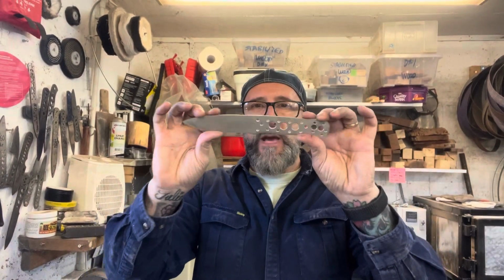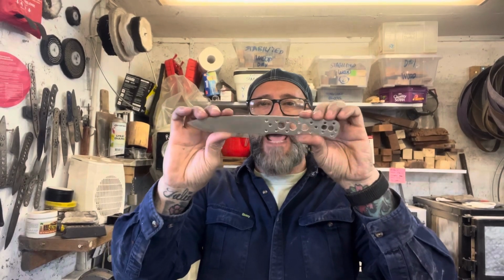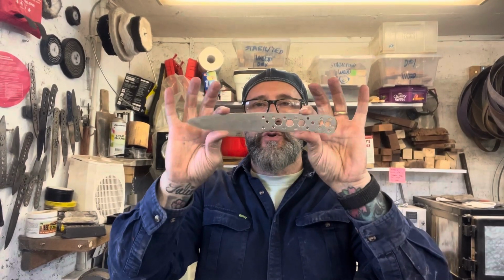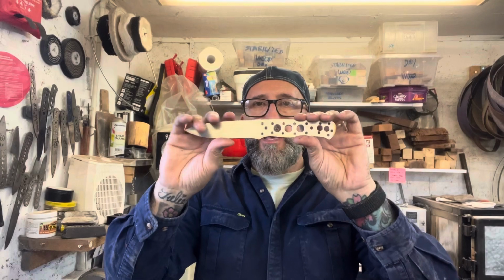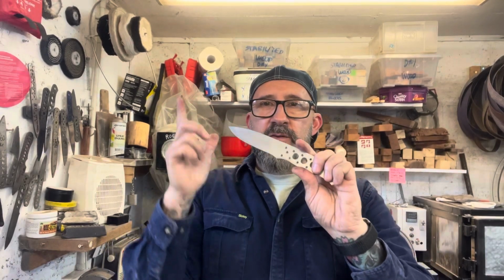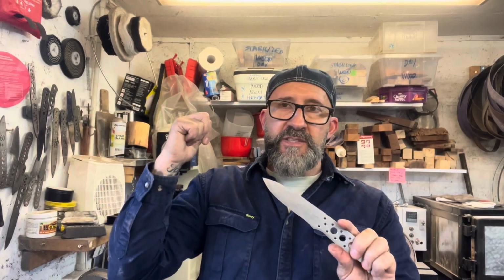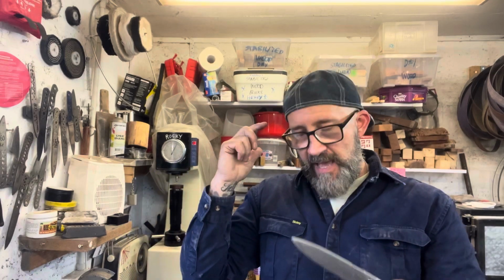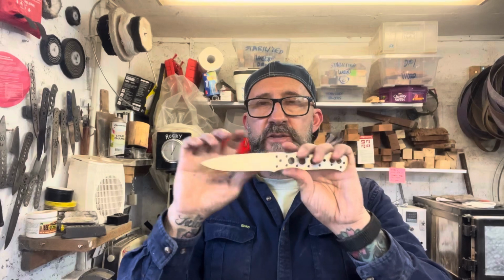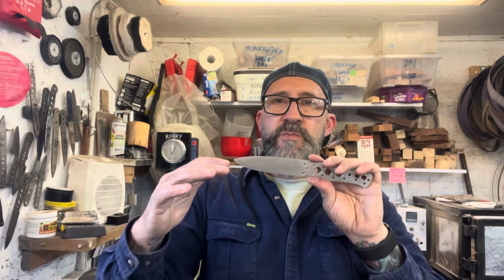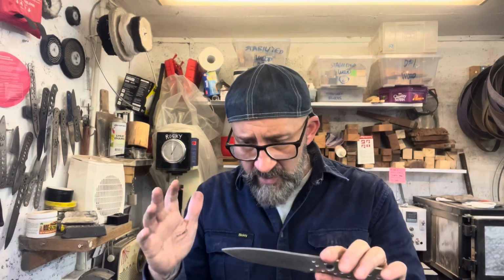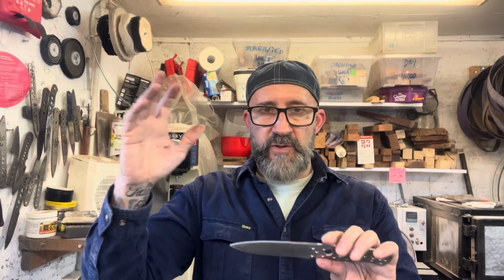Okay, so there we go. One hardened and tempered Bushwood original in AEBL. Prior to going in the freezer, I did the test on it, and that was at 57. And once it had the 4 hours in the freezer at -30, I took it out, let it come back up to room temperature, and did another test on it, and we were at 63. So we've had a 6-point increase from 57 to 63, which is absolutely perfect.